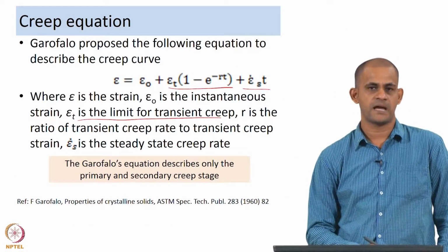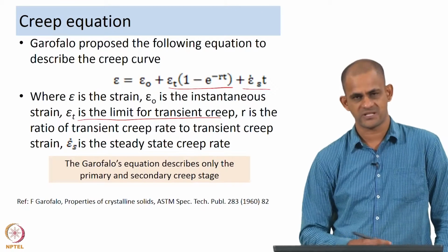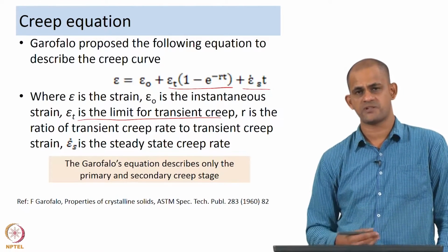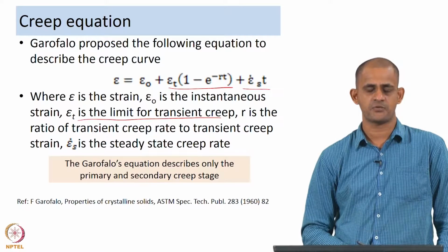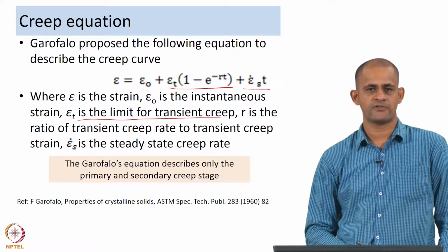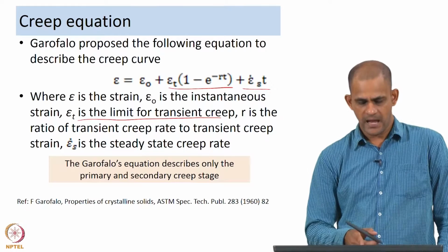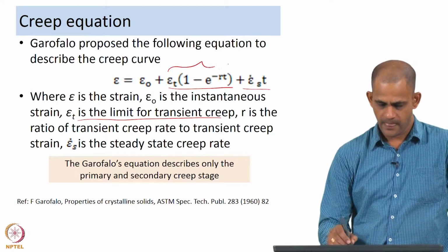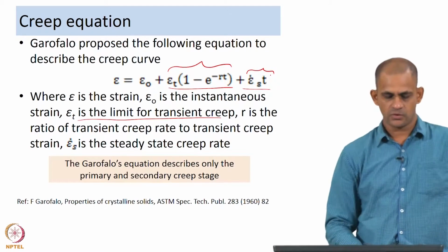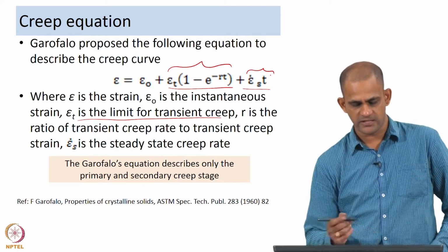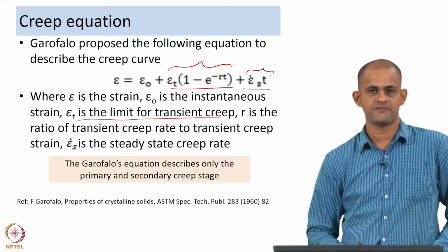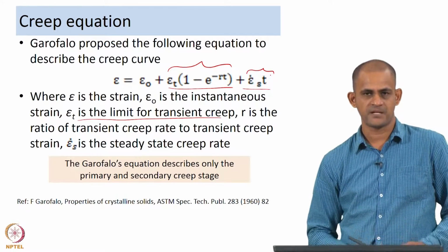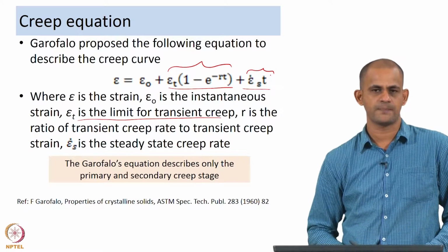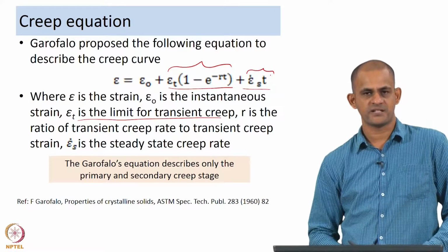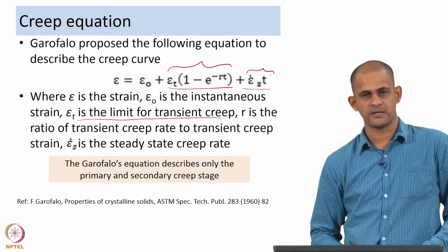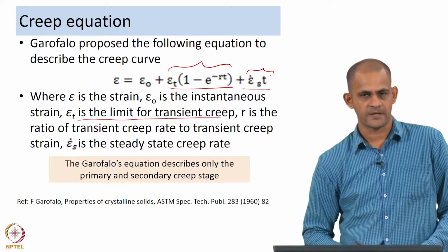In subsequent years, Garofalo proposed the following equation to describe the creep curve, and this equation was supposed to overcome the limitations of Andrade's equation. In this equation, Garofalo proposed that epsilon is equal to epsilon naught, and then there is a primary creep term and there is a steady state creep term. Here epsilon is the creep strain, epsilon naught is the instantaneous strain, epsilon t is the limit for transient creep or the primary creep region, and r is the ratio of the transient creep rate to the transient creep strain, and epsilon s dot is the steady state creep rate.